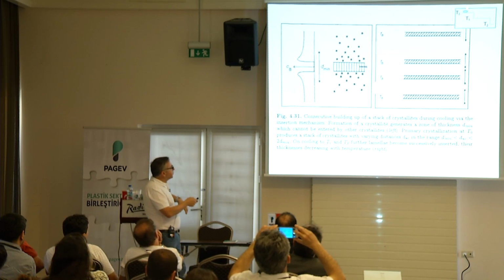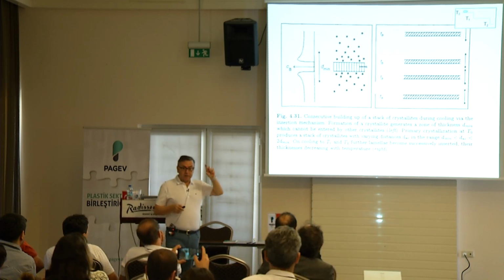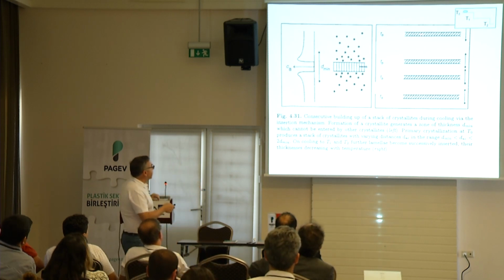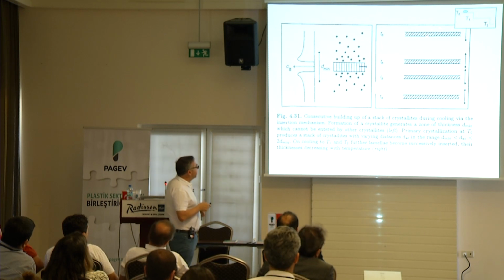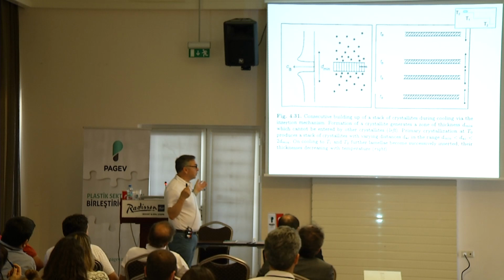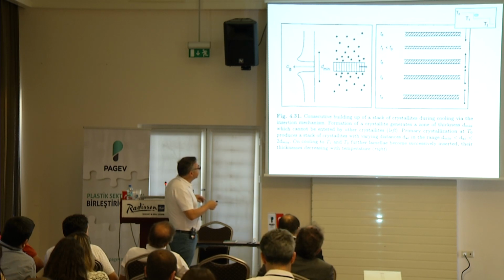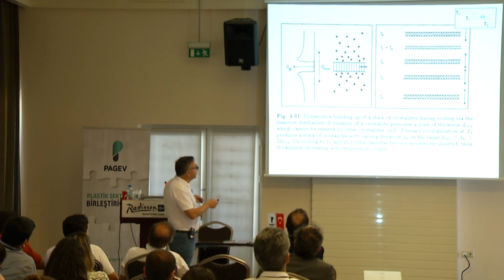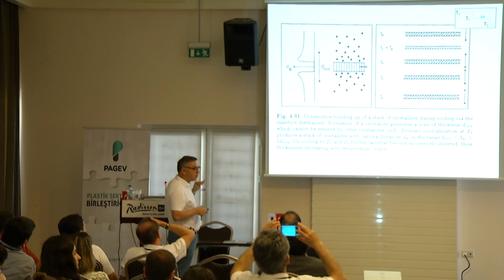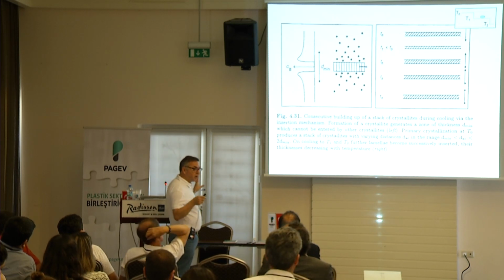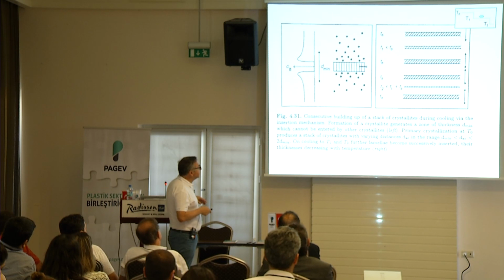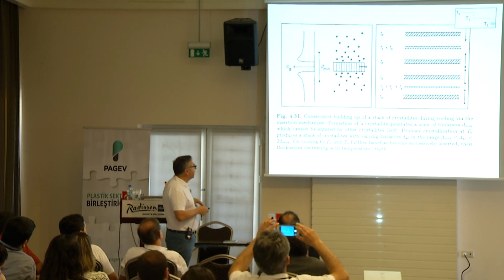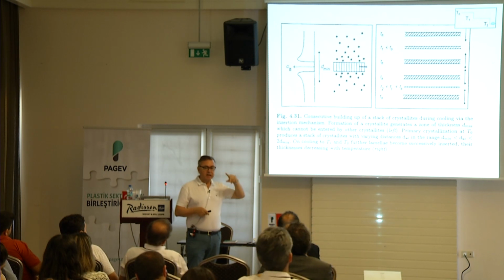What they found is that at high temperatures, and this is how you control the size of the lamella, remember we talked about it? At high temperatures, you have this large lamella growing because the material wants to grow at large thicknesses. If you go to a lower temperature, in between the pre-existing ones, you get the thinner one, because the crystal sizes become smaller as you go to a lower temperature. And we've already established that. Go to a lower temperature further, and crystal sizes get even smaller. So you have a distribution of lamella sizes as you do essentially three steps. In this case, it's a three-step process.